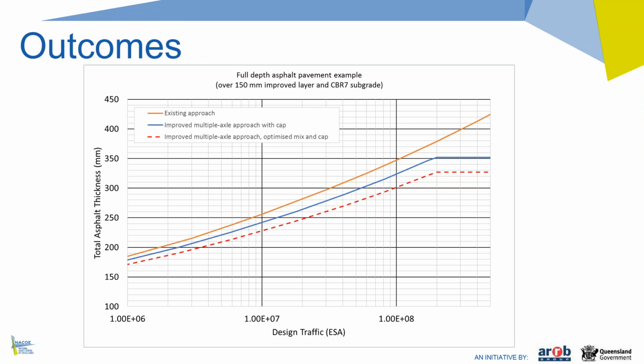Which was a motorway in southeast Queensland using the different design standards. This chart shows a similar comparison using the same full depth asphalt pavement structure, but in this case for a wide range of traffic loadings, which are shown along the horizontal axis. The top diagonal line there shows the required asphalt thickness using the current 2013 pavement design supplement and Austroads pavement design guide for a full depth asphalt pavement. The middle line then shows the required thickness when the new multiple axle method is used, 100 million ESAs that Jeffrey covered.